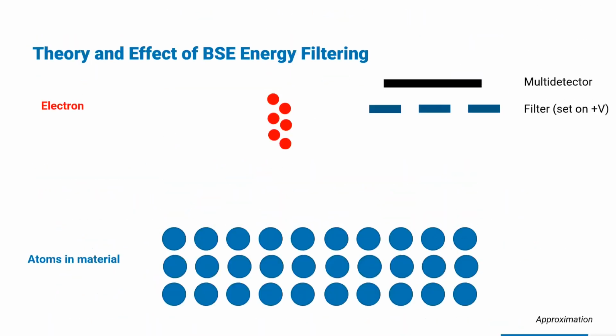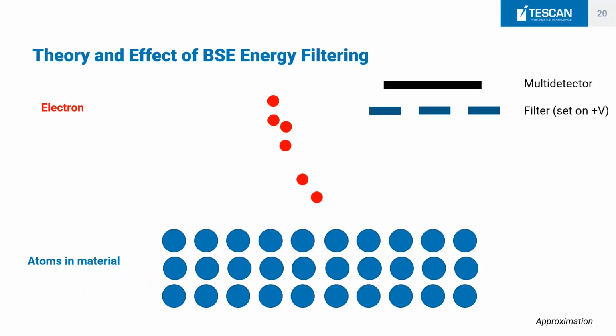That helps a lot, because when we have a detector, we can put a specific bias on the filter beneath the detector, and we can detect just those electrons which have higher energy and therefore didn't travel inside of the material too much. And that's what we did on that sample. We really detected just those electrons which were on the very surface of the sample, and therefore had enhanced surface sensitivity and contrast.